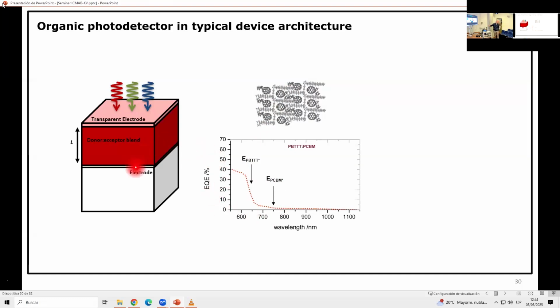And here you see such a quantum efficiency spectrum. It's not a very good detector or solar cell because it has 40% photon to electron conversion efficiency above the gap. And then here is basically the band gap or the optical gap of the polymer. The fullerene, that's why we don't use them anymore, doesn't absorb much light, but that's this little bump here. And then here, it looks like there's a very small amount of absorption, but who cares because it's less than 1%. It's not really contributing to anything. You can't really use it.